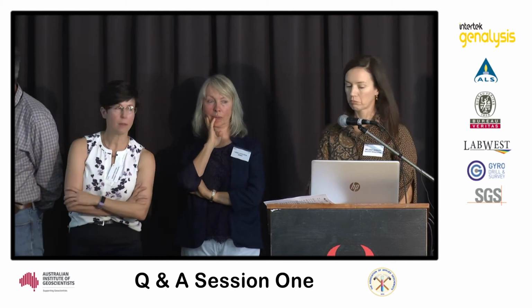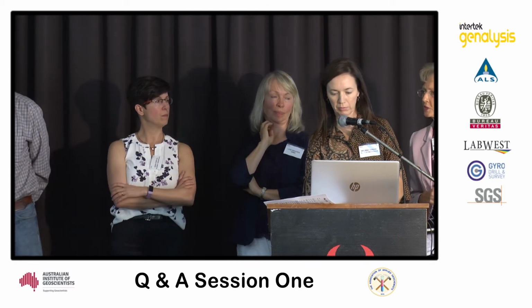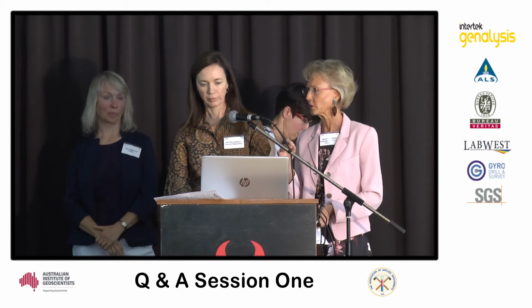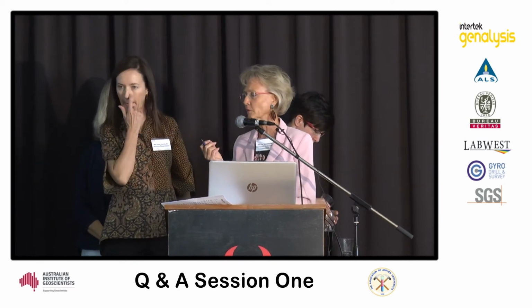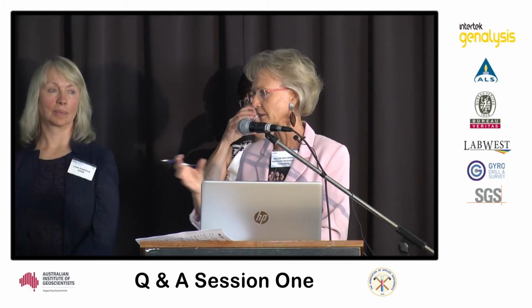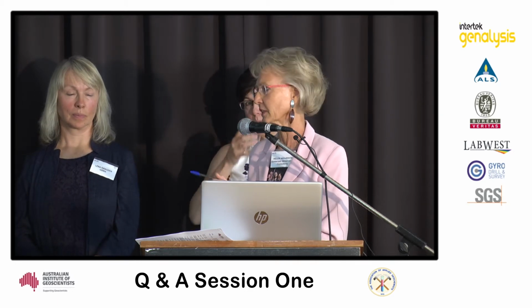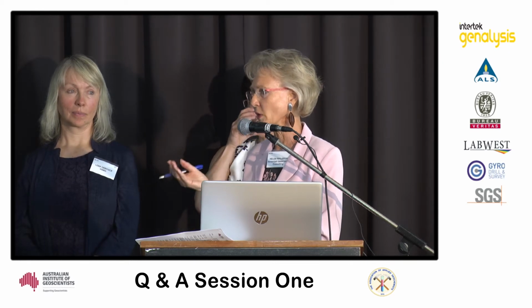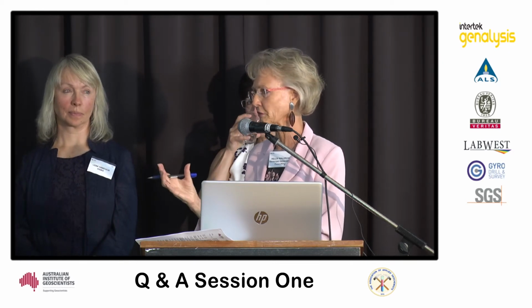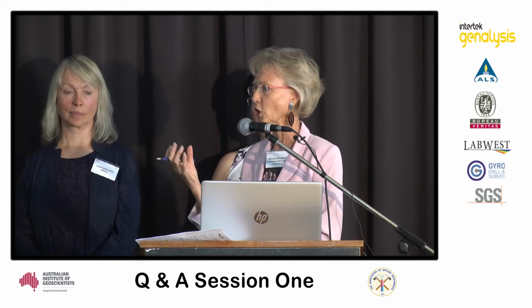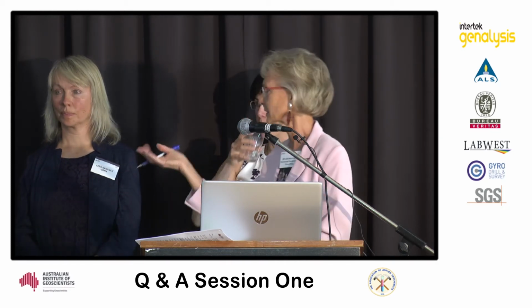We actually did a test many years ago when I was still working with Genalysis for that very reason, to see if it could actually fit into a standard lab flow process where most things are done on pulps. So we did a large test. We took core material and then we crushed it to various sizes, dried it and looked at various variations. Certainly, as Sasha was saying, you do get a degraded signal. You just get too much reflectance. However, you still can see the dominant features. So if that's all you've got, I suggest it's worthwhile trying. It's not the optimum material that you'd go for if you're able to start from scratch, but you still can see the main features. Melissa?